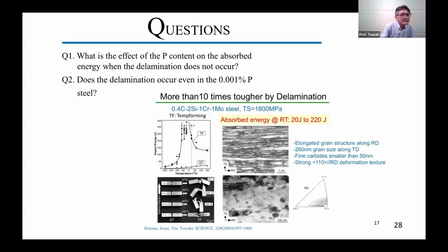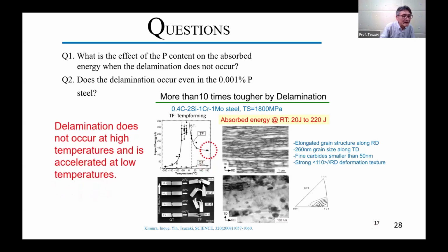The clue is on the previous slide, number 17. As shown here, delamination doesn't occur at high temperatures and is accelerated at low temperatures. Therefore, to answer question 1, we can do the impact test at high temperature. And to answer Q2, we should do the test at low temperature. So all we have to do is to get the Charpy curve of the impact energy of the TF and QT sample with different P content.